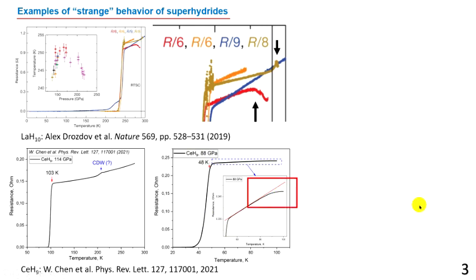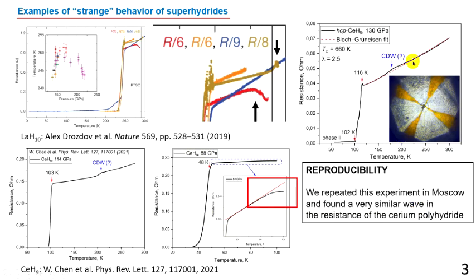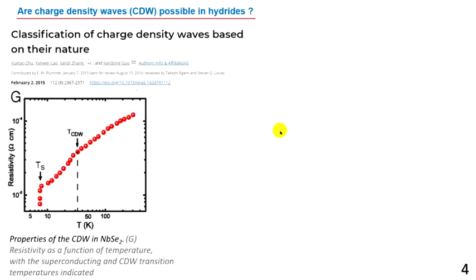And we were able to reproduce this feature, this wave in the resistance curve, in our Moscow laboratory. We synthesized at 130 GPa the same compound, cerium H9, and measured the dependence of electrical resistivity on temperature. And you can see the same wave appeared in our experiment too. So it's a reproducible feature. So we need to think what can help us to explain this phenomenon. What may be the reason for this phenomenon? So my question is, are charge density waves possible in hydrides?